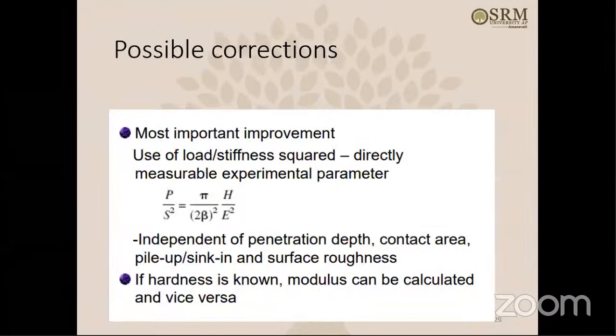Okay. So, possible questions for this load frame compliance and everything. Use of the load versus stiffness squared parameter. Oliver and Pharr suggested the use of this parameter, load versus stiffness squared, which is equal to these values here: hardness, modulus, beta, and all these factors. So if you use this directly measurable experimental parameter, load versus stiffness squared, this parameter is independent of penetration depth and contact area, and is also independent of pile up and sink in errors and surface roughness. It doesn't care about depth, it doesn't care about area, it doesn't care about pile up, sinking errors, or surface roughness. So you can use this to adjust the compliance. If hardness is known, modulus can be calculated and vice versa.